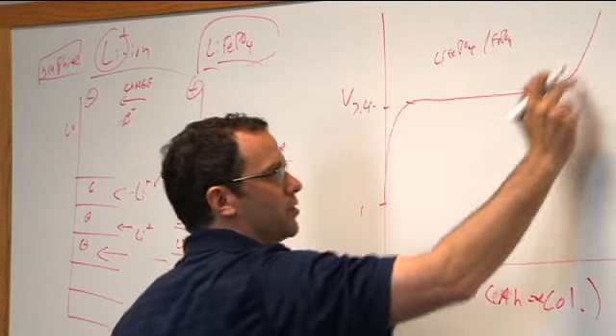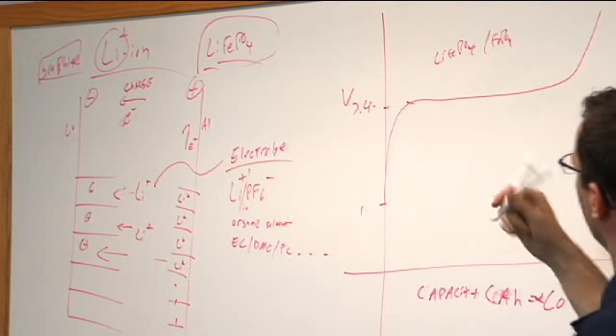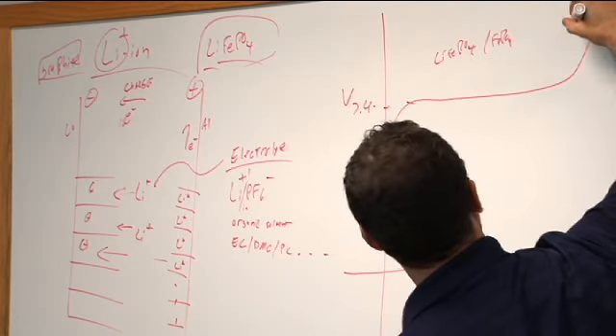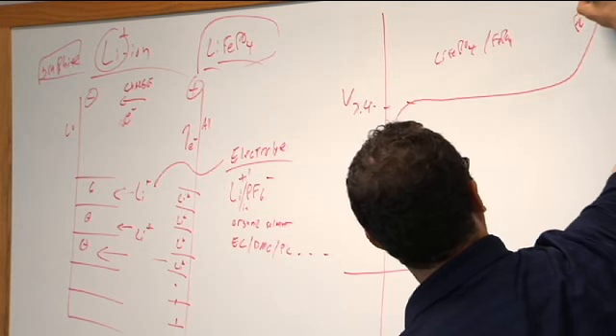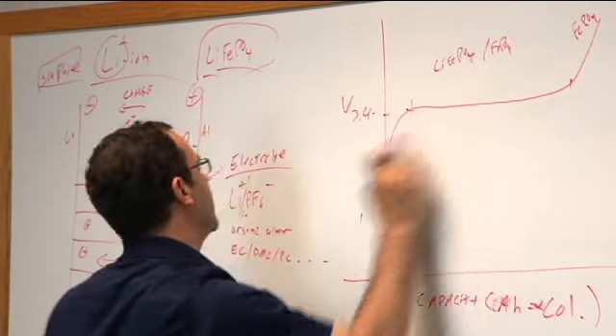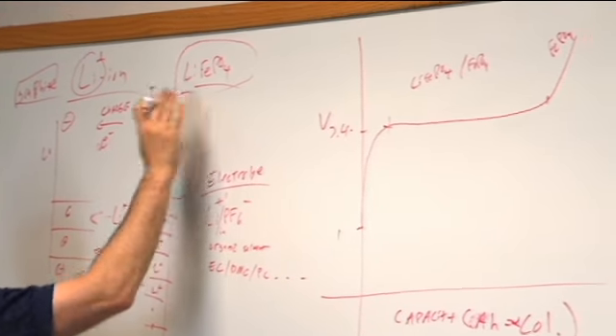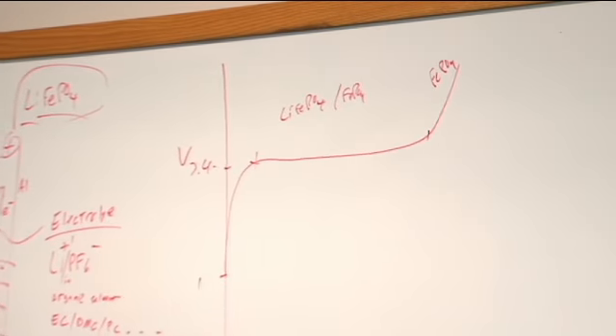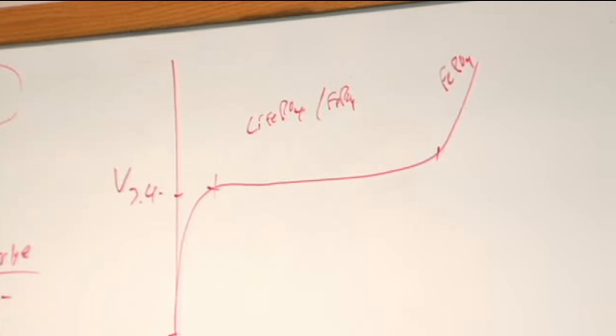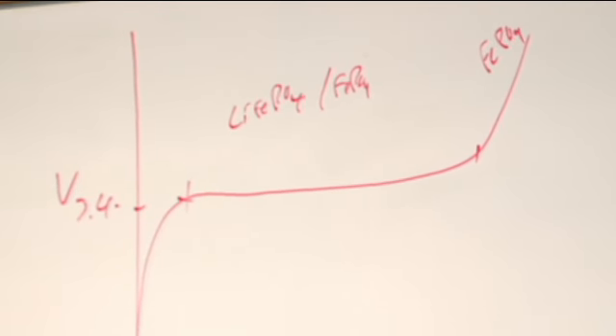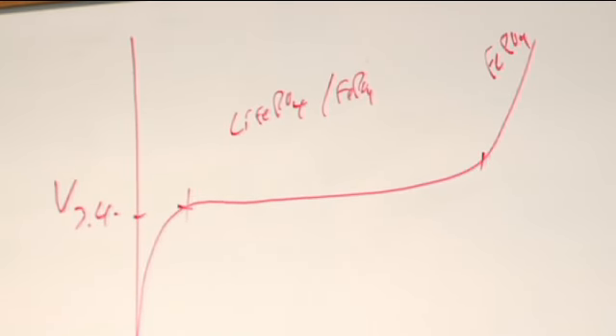And up here, when it starts to curve up again, you've exhausted all the lithium out of the system, and you are left just with FePO4. Okay? And so that's sort of what's happening. Within this voltage range, you are enacting a phase change between lithium iron phosphate and iron phosphate, by removing the lithium from the lithium iron phosphate crystalline material, extracting it into the electrolyte and driving it into the graphite that's over here on the anode side.